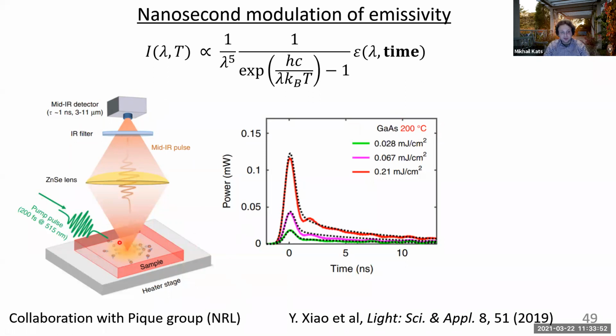And then you hit it with a pump pulse at a wavelength that's much shorter than the band gap of gallium arsenide, and you generate a whole bunch of free carriers, right? And then because you generate all these free carriers, if you calculate the Drude response, the material becomes quite lossy in the infrared, and your emissivity goes way up. And so then your thermal emission power goes up.